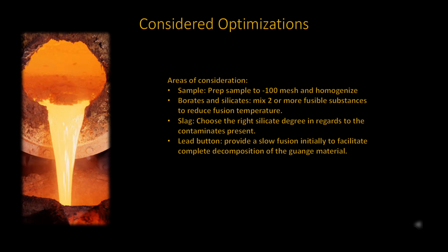The slag becomes more viscous as more borax or silica is added. As the borax and silica are acidic, the slag becomes more acidic. The acidity is also dependent on the impurities in the ore. One needs to know which silicate degree to use for the fusion, and it is used to calculate the charge constituent.